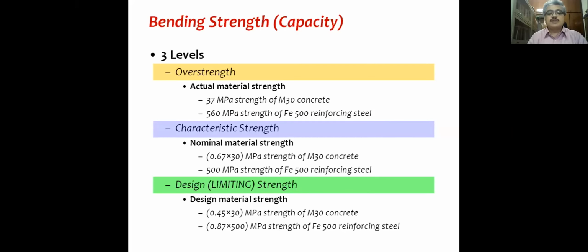But then we know this so-called characteristic strength is the 5%. That means it is expected that in 95% of the cases, actual strength of the material will be higher. For instance, if you go and buy Fe 500 steel from the market and come back and test, you are supposed to get a strength more than that. So let's say you get something like 560, which is 12% more. When you say M30 concrete, actually if you go and test, you're supposed to get an actual strength higher than that. And that means there is what is called an overstrength.